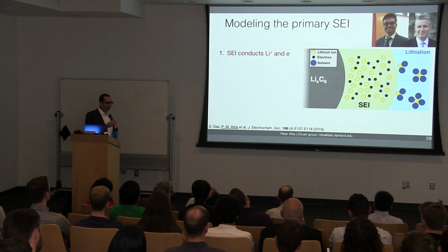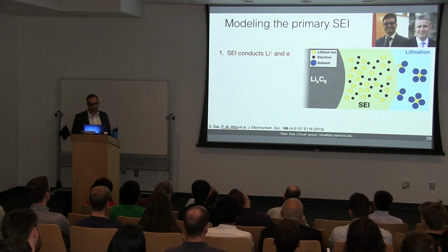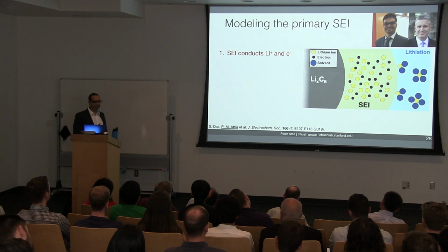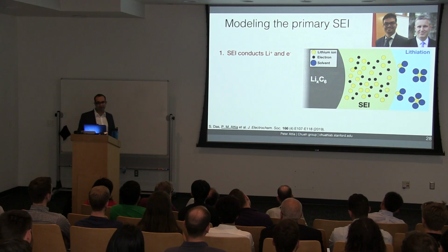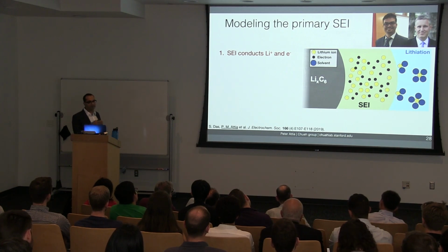But even though the SEI conducts both electrons and ions, the ionic conductivity is much higher than the electronic conductivity, because the timescale for lithium ion insertion is minutes, and the timescale for SEI growth is really hours, or weeks, or months. And there are two relevant features of mixed ionic electronic conductors here. They are electroneutral, meaning the concentrations of both lithium ions and electrons are equal. Another important aspect is that the concentrations are dynamic, which is important to capture this phenomenon.